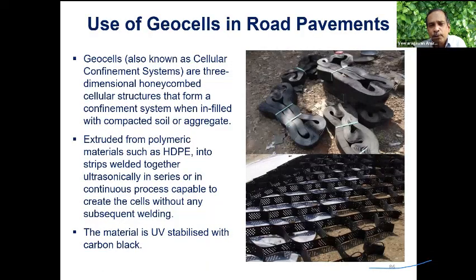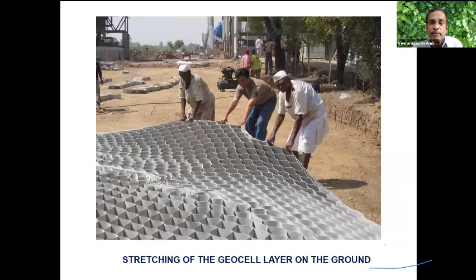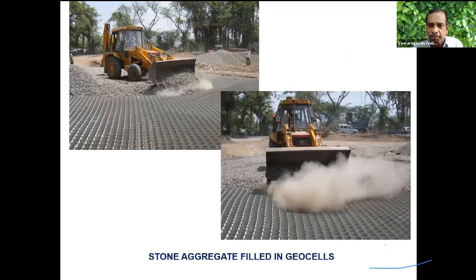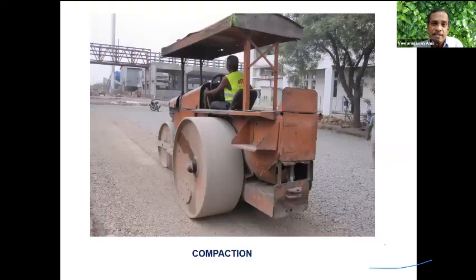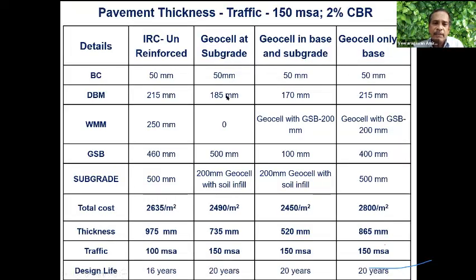I think it's time that we also look beyond outdated materials. I think it's time that we look at geosynthetics. I'm a fan of geosynthetic materials. These geocells can be effectively used. I have demonstrated that they can be effectively used. They are UV stabilized with carbon black. What are the benefits? I did a project, a typical project in Maharashtra. Geocell can be stretched, laid, and filled with aggregates. By adopting this geocell in the granular layer, if I have a thickness of 975 millimeter, if I use a geocell as a subgrade, I can bring down the thickness from 975 to 735.